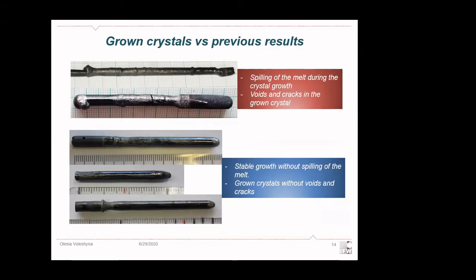And as a conclusion for this part, I can say that using other growth parameters, such as higher oxygen pressure in the growth chamber and lowering of the growth rate, can prevent the spilling of the melt during growth, cause stable growth of the crystal, and lead to obtaining crystals of high quality.